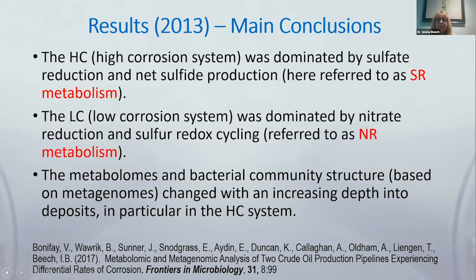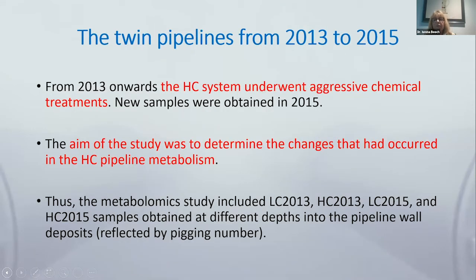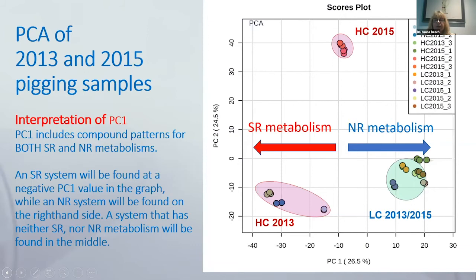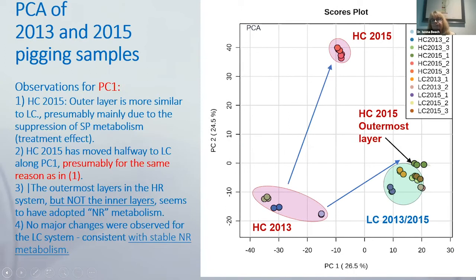So these high corrosion systems were dominated by sulfate reduction, the low corrosion systems by nitrate reduction. But what is very important is that we then compared the shifts in these same pipelines when people started treating, trying to prevent corrosion, so with different types of corrosion inhibitors, etc. And what we found is that we could shift the system by whatever mitigation strategies people applied, but it was not obvious that the depth of corrosion, I mean of the material, was affected.